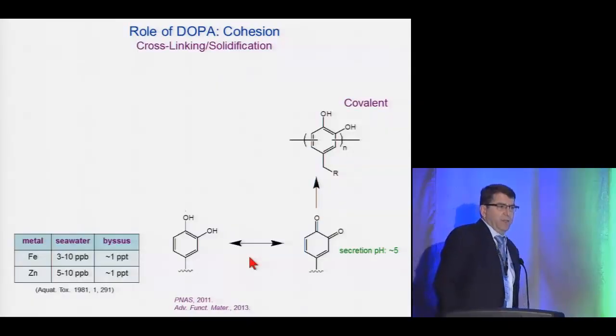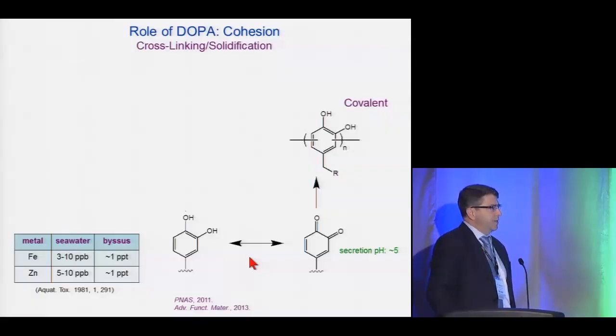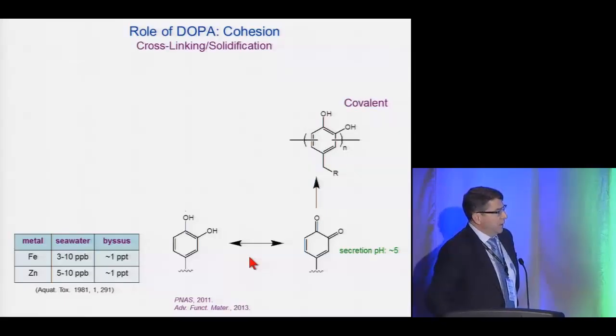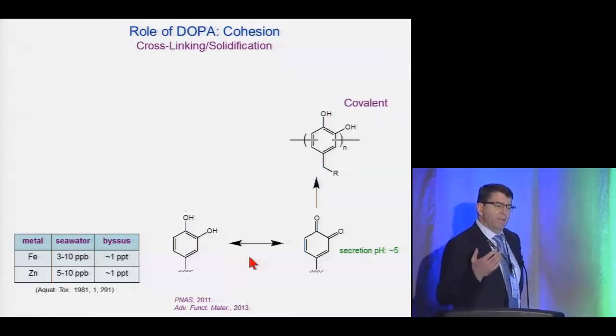It turns out that the mussel byssus is highly enriched in metals. I've listed two of them here, the two of the more important ones for our research, which is iron and zinc. In both cases, the byssal tissue has about 5 orders of magnitude higher metal concentration than the surrounding seawater. And it turns out that the mussel mobilizes these metals and co-injects them with the proteins during formation of the byssus. And so there's a lot of interesting questions about what is the mechanical role of the iron. Why is it there? There's nothing diffractable in terms of mineral content in this tissue.